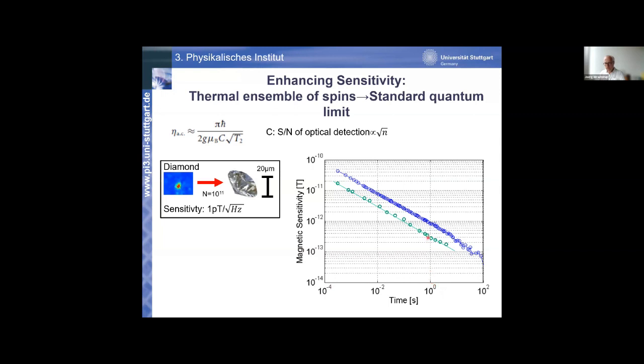Typically we calibrate everything to 1 second measurement time. And this is what people routinely achieve these days with these types of sensors. For ensembles, with a small n on the order of 10 to the 10, 10 to the 12 defects or dopants, you achieve a sensitivity of 1 picotesla per square root of Hertz. This greenish curve here is the recent improvement we and others have been working on, so you get a bit below this value, to a few hundred femtotesla per square root of Hertz.